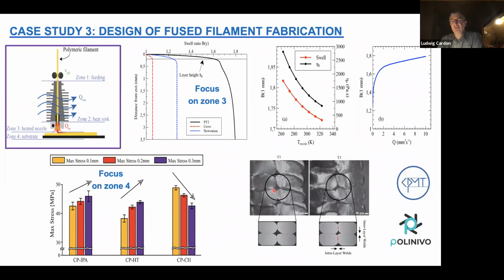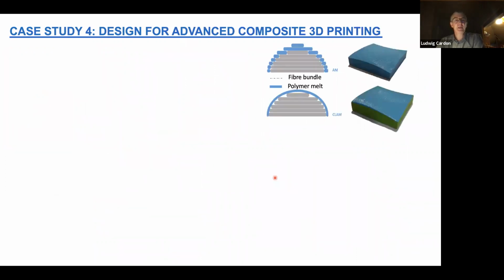It's some stereoelectron microscope image. So these very small voids, we try to reduce them by optimizing, let's say, the shear effect by reducing the die swell and so on. So there is a lot of combination of flow behavior and material science for the so-called welding of the strands. So that briefly tried to illustrate how we combine again material science and machine development and engineering.